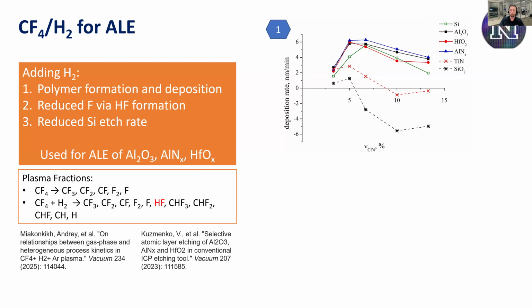So we're going to pick something from all this work that we've surveyed. There was maximum deposition on silicon at 6.7% CF4, 26.5%-ish hydrogen, and balance argon. We're going to use that. Now, a little bit different from what people have been doing before: yes, we're going to modify our surface, but we're also going to deposit a polymer and have some buildup on top of that surface. Then we're going to remove that polymer, which is really easy to remove in argon, and also remove the modified surface, without damaging the underlying material.